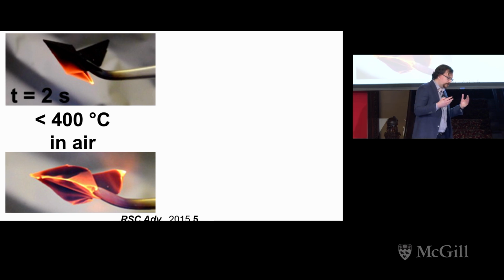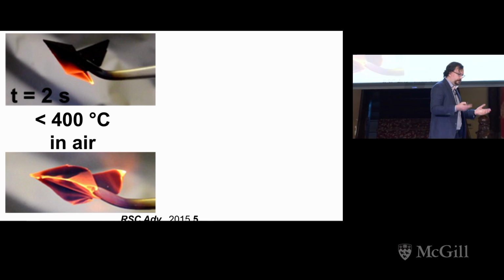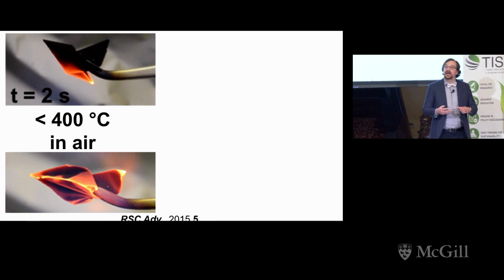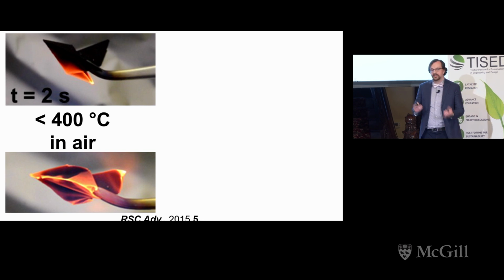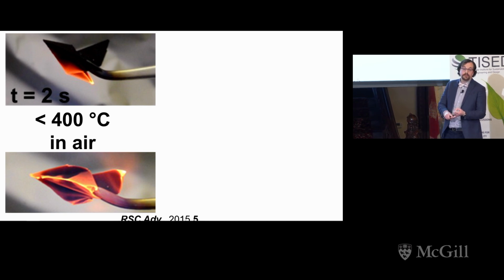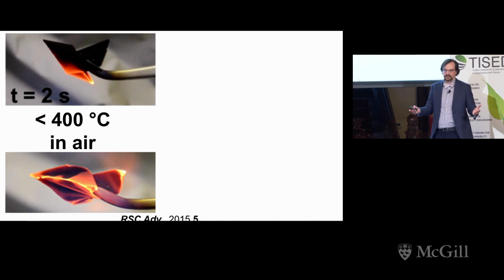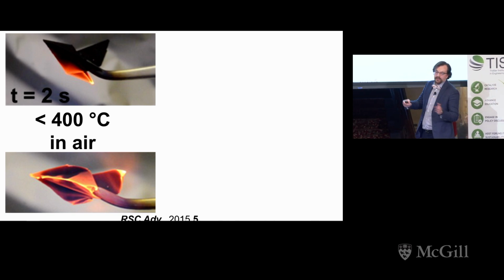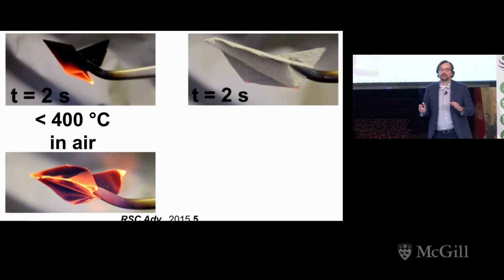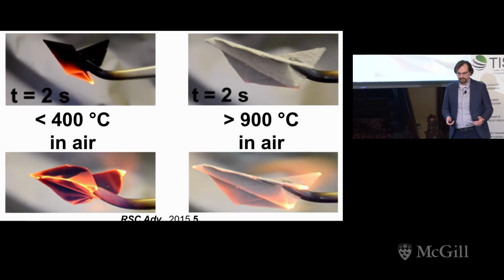One of the potential solutions is to use a material with the same tubular structure we want and a similar surface area. However, this material is thermally stable over 900 Celsius in air, and it's called boron nitride nanotubes.